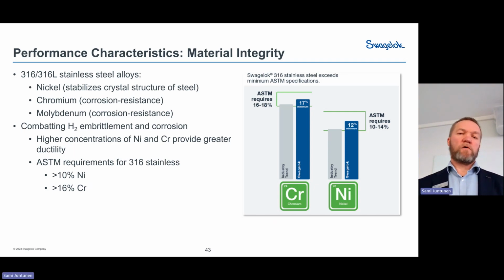About the material side, let's talk about stainless steel, Swagelok stainless steel. The main components with iron are nickel, chromium and molybdenum. Nickel is a stabilizer for the crystal structure of the steel. Chromium and molybdenum are there for corrosion resistance. The ASTM standard says that for 316 stainless steel, the nickel content needs to be 10 to 14%, and the chromium content 16 to 18%. Swagelok decided years and years ago that nickel content needs to be 12% and chromium content needs to be 17%. In that way, our Swagelok material will be much more corrosion resistant than other 316 materials.